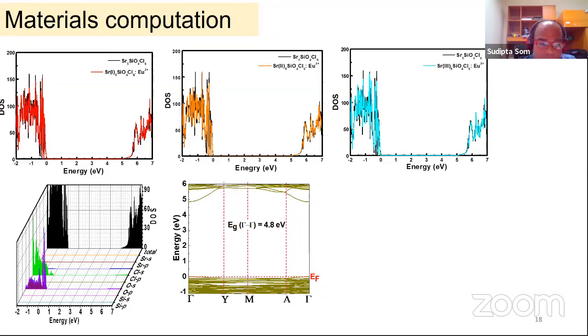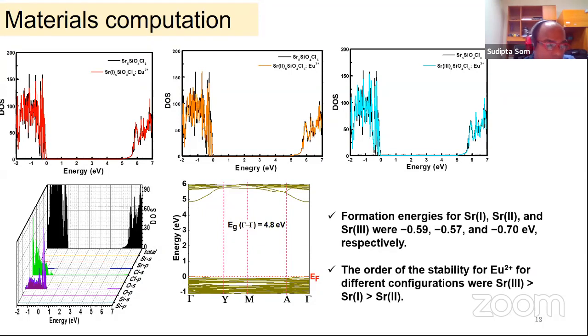Now, what will we get from these DFT calculations? From this calculation, we can get an idea about the formation energy of each site and of the material, along with the band distributions and band gap also. The formation energy is the indicator of the stable configuration. If our formation energy is very negative, our material will be stable. Whatever materials we have chosen, we did the DFT, and from there we selected only the stable materials for this study. And I think you can understand up to this point.